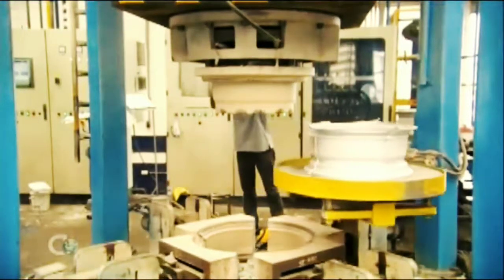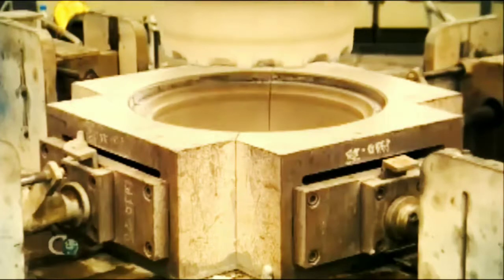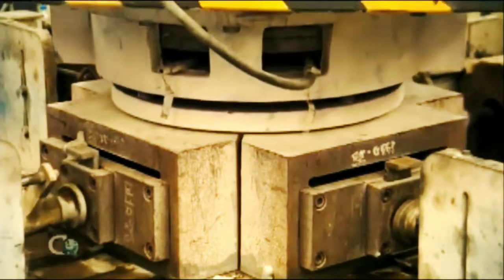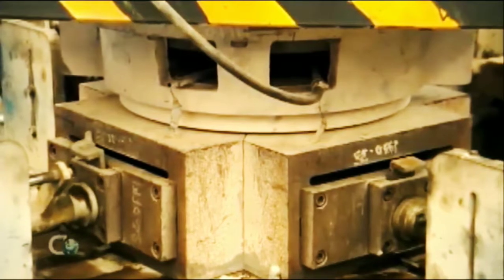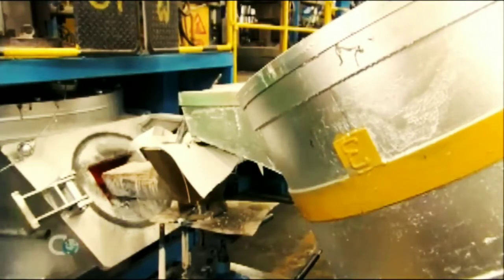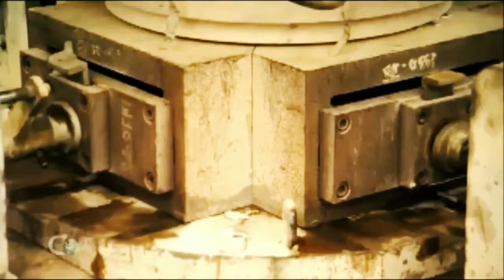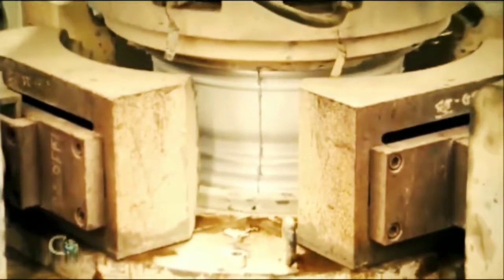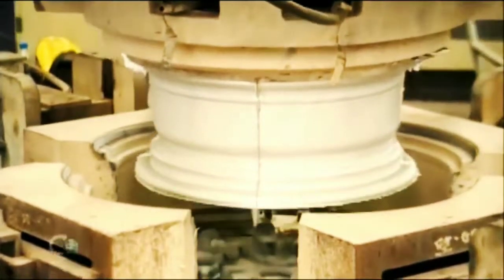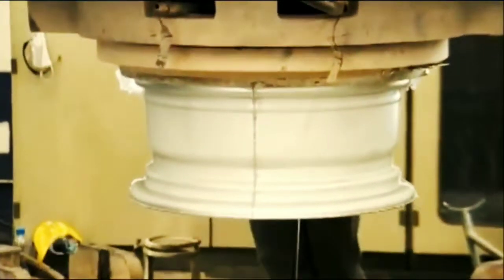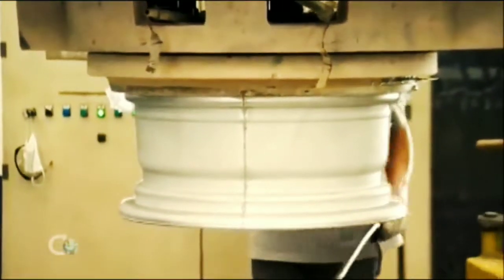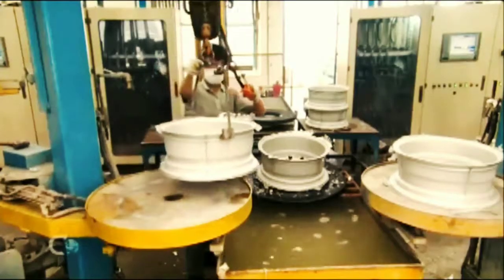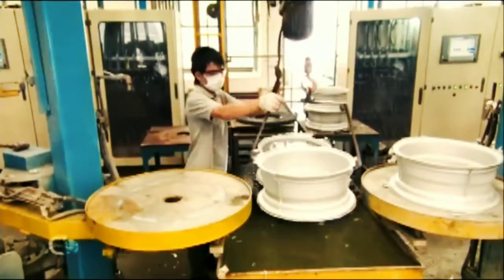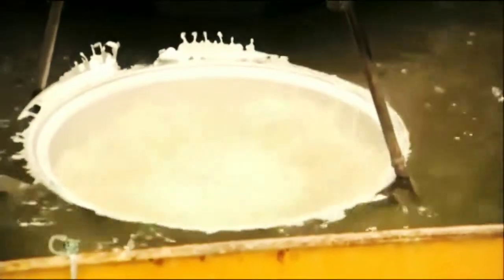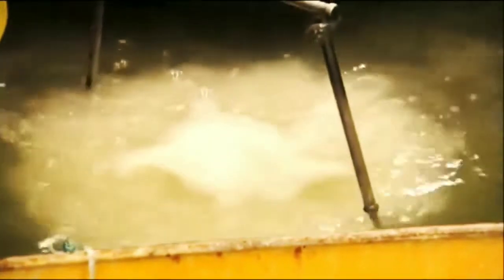The casting machine is designed to fill the mold from the bottom by pressurized injection. Injecting upward through the bottom, rather than pouring downward into the top, reduces the risk of air bubbles, which cause defects. Right before casting, the molten metal flows through a filter sheet made of high-temperature resistant ceramic. This traps additional aluminum oxide. Once cast, the aluminum takes about 7 to 10 minutes to solidify. Then the mold automatically opens, releasing the newly cast wheel. Workers submerge it in lukewarm water for a few minutes. This cools it down enough to be handled.